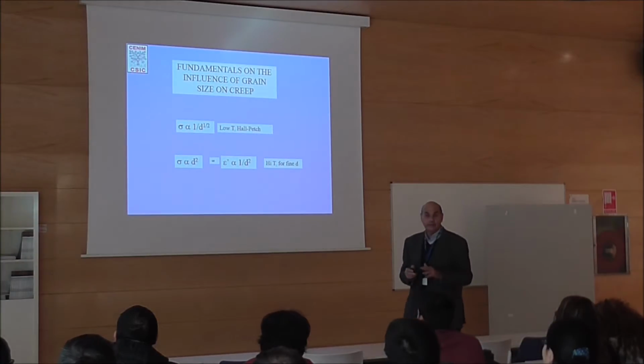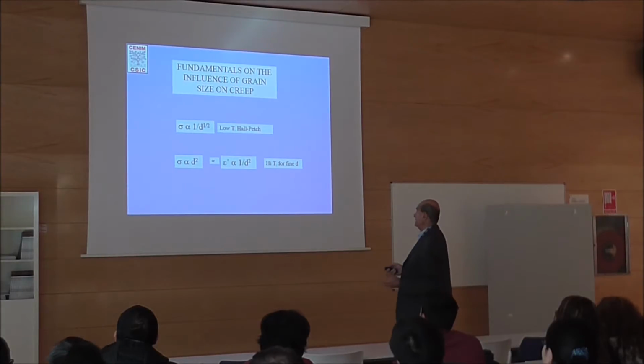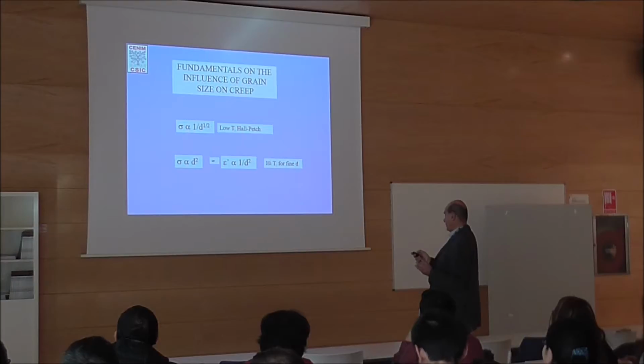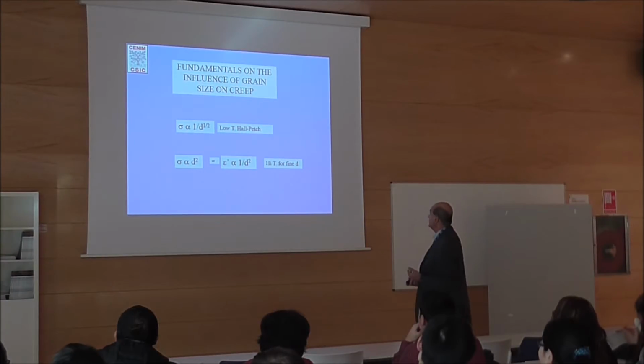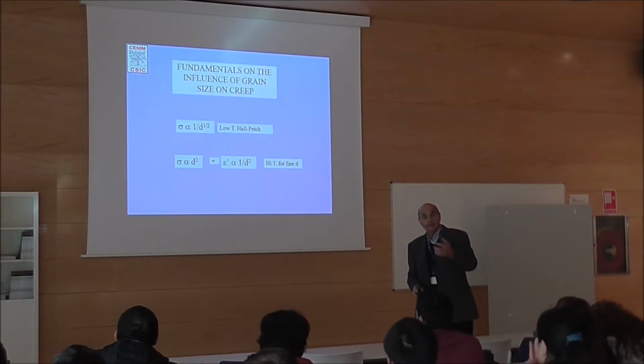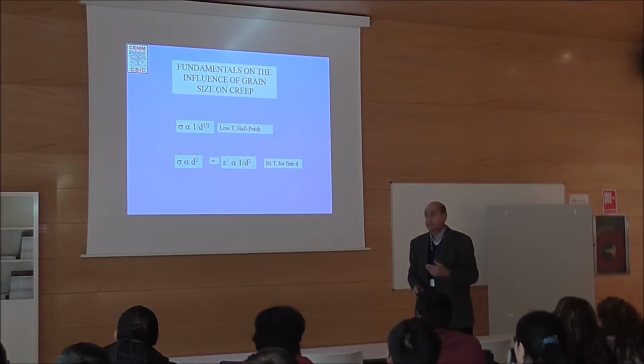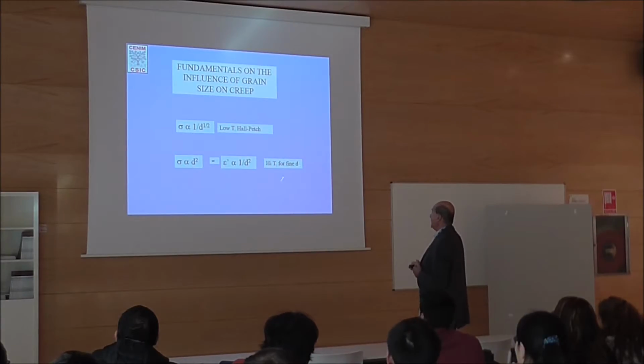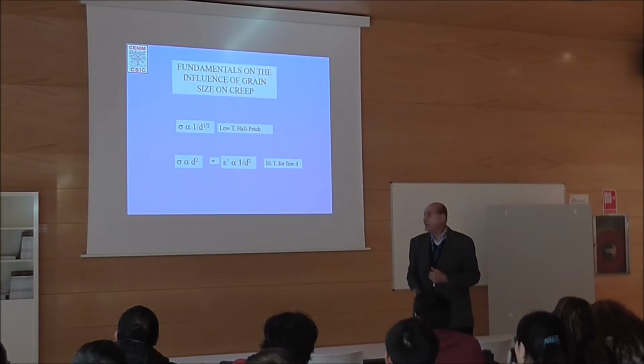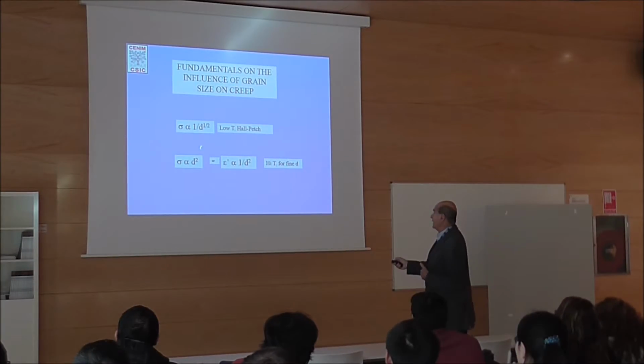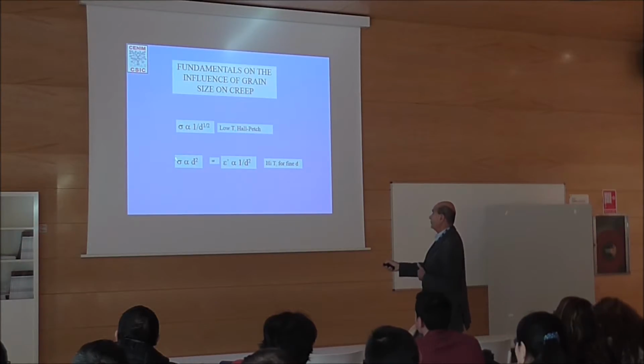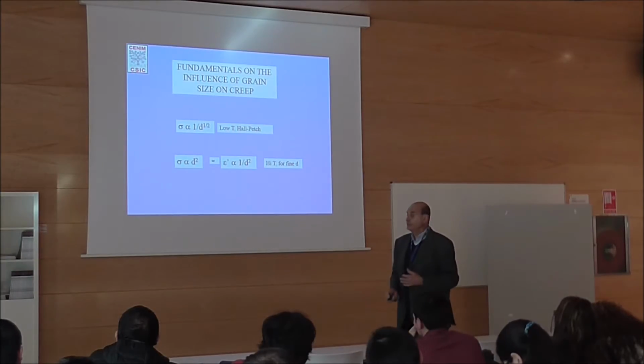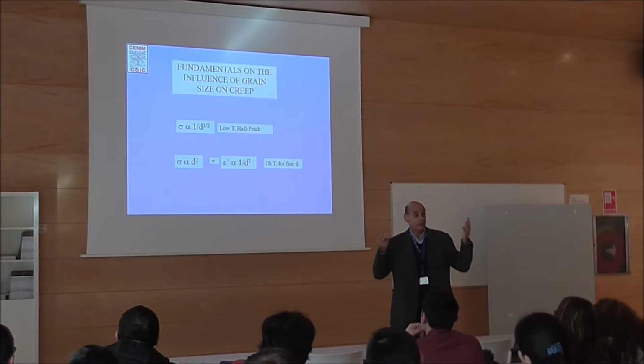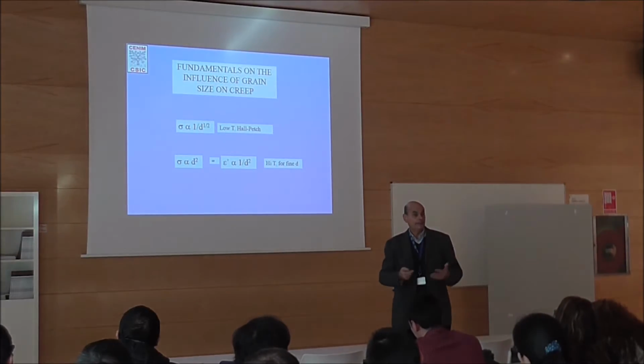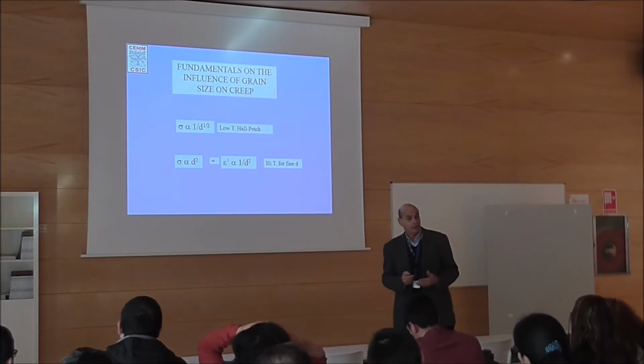Okay, here, up to here, I said, is not dependent on grain size. At low temperature, we have the so-called Hall-Petch relation, where stress is proportional to 1 over d^(1/2), which means that the finer the grain size, the tougher the material, the more resistant the material. But now at high temperatures, when we have very fine grains, strain rate is dependent on grain size. And it is exactly opposite to low temperature. So the stress is proportional to probably the square, sometimes to the cube. And now the question is what's going on. You just told us that strain rate will not depend on grain size.